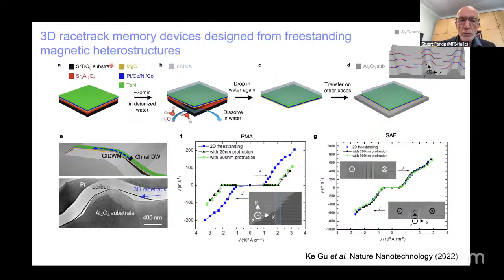On this substrate, we first grow, using pulsed laser deposition, this strontium-3 aluminum-2 oxide-6. This is an oxide material which is water soluble. On top of this oxide material, we grow first a buffer layer of tantalum nitride, and then on top of that, we grow the racetrack: a platinum layer, the spin orbit layer, cobalt, nickel, cobalt, and magnesium oxide.